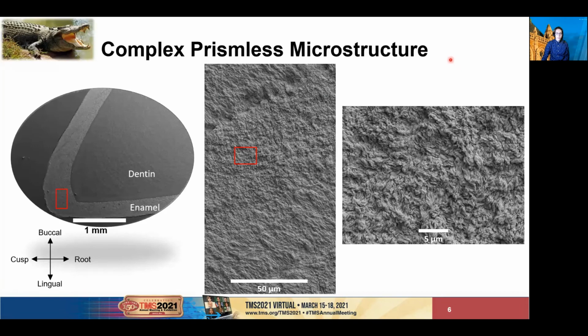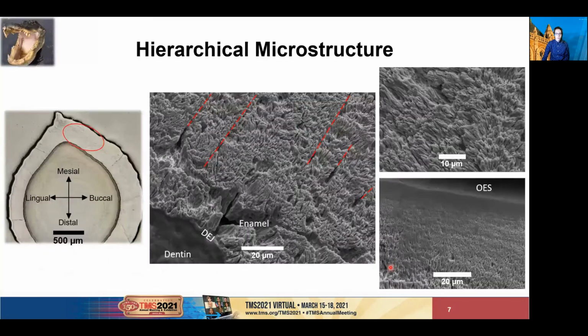This is another polished and etched buccal lingual section of the cusp of a tooth, this time from a saltwater crocodile. It is possible to see distinct bands where the nanocrystals are parallel to the exposed surface as before, here at the top and the bottom of the micrograph, but there's also this region separating them, where we're looking down at the hydroxyapatite crystals along their long C-axis. Clearly, there is some three-dimensional complexity to the microstructure, so we need to add another perspective.